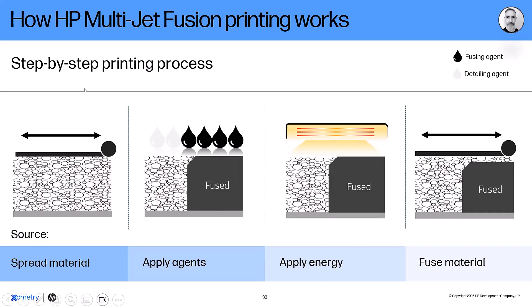During this process, you're fusing down through multiple layers, which gives you essentially isotropic properties in X, Y, and Z — a big differentiator between other technologies in powder bed fusion. The speed is also notable — it's an area-wide pass. Every single layer, depending on the system, can be anywhere from six to twelve seconds per layer, regardless of how many parts are on that layer. It could be one part or 1,000 parts — it's always a static layer time, giving you full build volumes in a static time. The 5200 series in PA-12 balanced print mode will finish an entire job in 12 hours. Depending on each material, you'll have different variances in build time, but it will always be a static build time for the entire volume. Once it traverses, disperses the agents, and exposes to infrared energy, you cover that layer with powder again and repeat throughout the build.